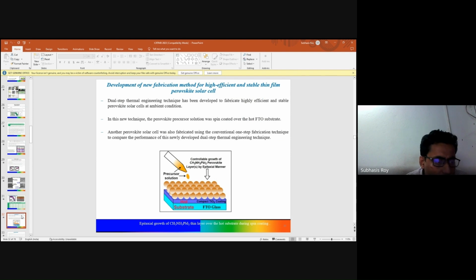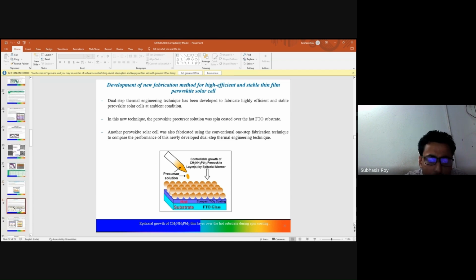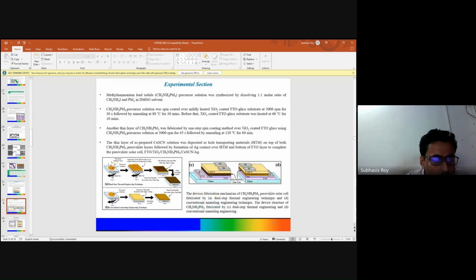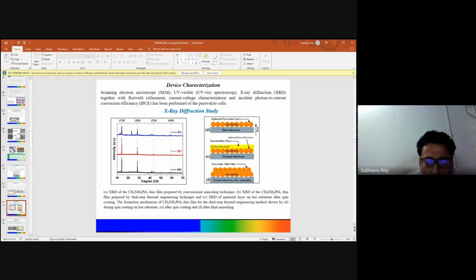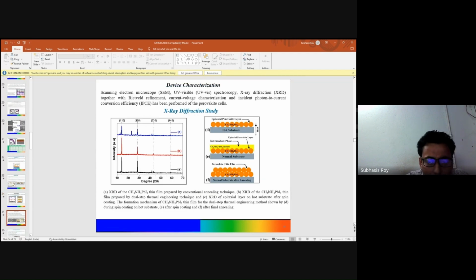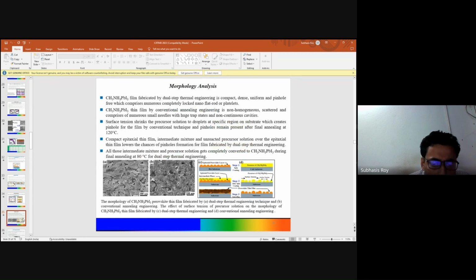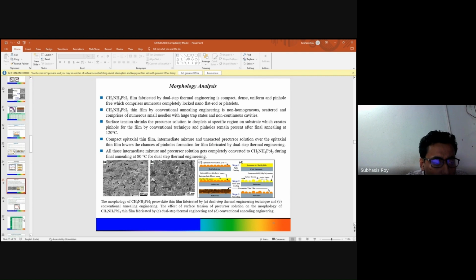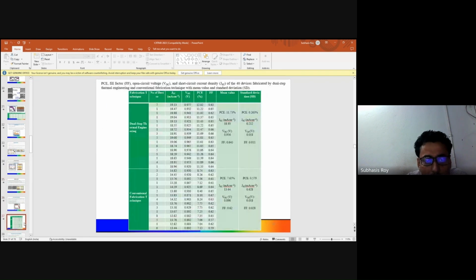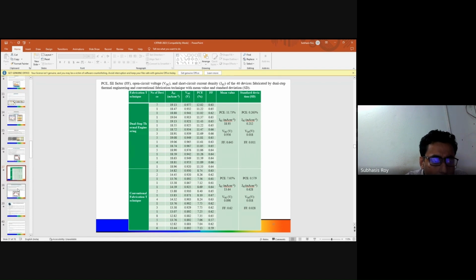In this way, we have also done different types of studies. We changed the fabrication techniques, like thermal engineering techniques, to fabricate these perovskite solar cells and try to improve their efficiency. And this is the thermal engineering technique, where we did two types of thermal heating inside the thin films to make them more stable. And finally, we checked the efficiency increase in the dual-stage thermal engineering system, and it is giving an efficiency of around 12%. That is much more than in the comparative study.